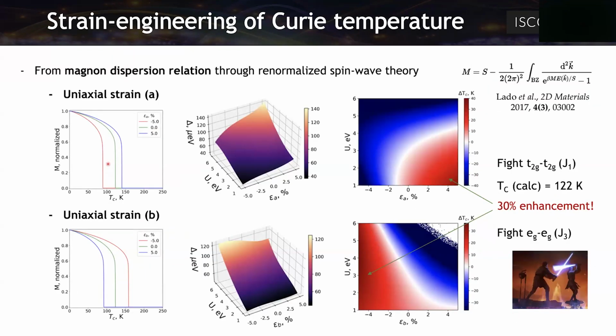Then we calculated the Curie temperature of the material from the magnon dispersion relation, using renormalized spin wave theory with this self-consistent expression. That was reported by Lado et al. in this work. In this case, we can observe that we achieve a value of 122, the experimental is 146, so it's pretty close for this kind of prediction. And we can observe that when we are increasing along A, the material is expanding and the Curie temperature is being enhanced.